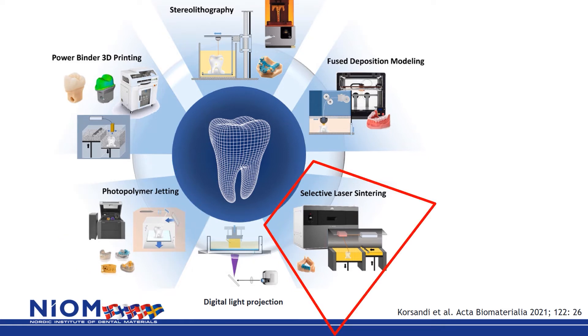Selective laser sintering (SLS) uses a high-energy laser to create sufficient temperature to induce fusion of a powder, creating the three-dimensional object. The powder is often metallic and the laser heats the metal powder almost to the melting temperature so sintering occurs. The powder may also be a ceramic, often with incorporated binders, or even a polymer, requiring much less energy. One important advantage of SLS is that the object may be printed in its final shape without additional supports. However, an SLS printer is quite expensive.